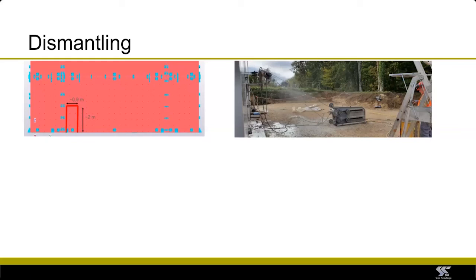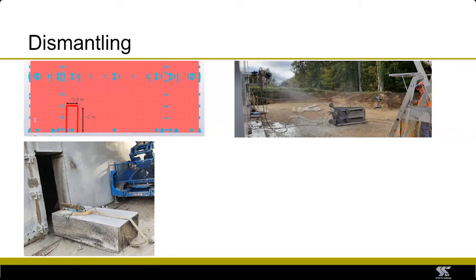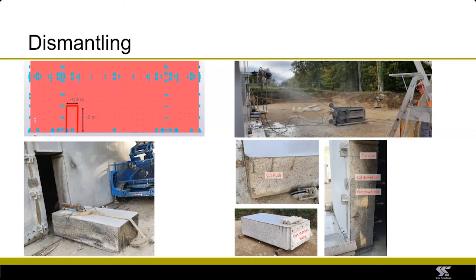In addition, we wanted to look in the project at how you would dismantle some of these structures. So we used a chainsaw to cut a door through one of the modules, and you can see the cut door there. Again, that technique proved to be quite straightforward to use for this type of construction. And it's interesting here because you can see the quality of the concrete around the shear studs, around the starter bars and the dowel bars.